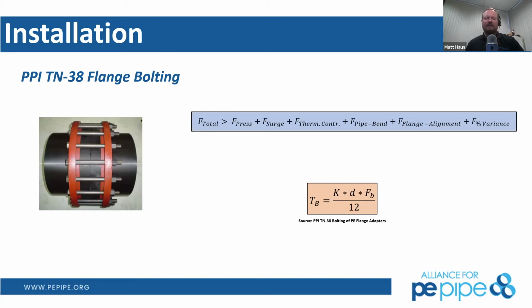Similarly, the design seating stress for HDPE, in order to obtain like a 2 to 3% strain, which will generate enough sealing pressure, is between like 1200 and 1800 PSI. So by comparing the two numbers, the MOBL and the MSF, the minimum sealing force, you take the highest of the two divided by the number of bolts, and that'll be the force that you'll be generating, and you can calculate the bolt torque necessary to achieve that.